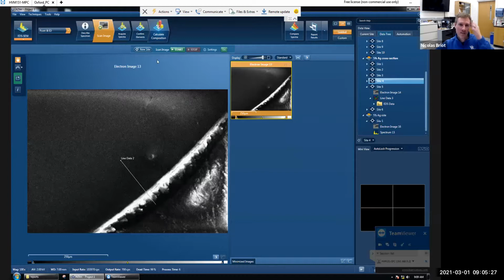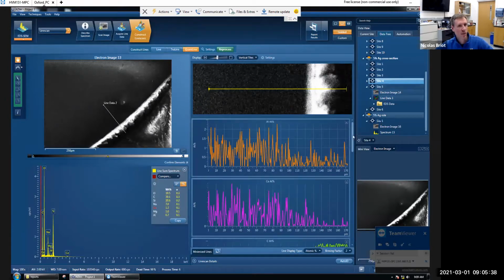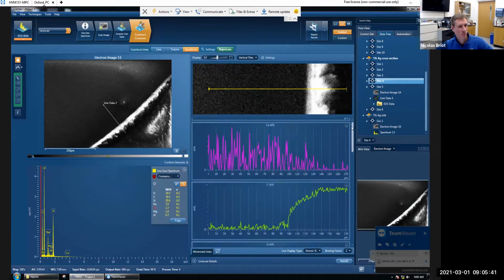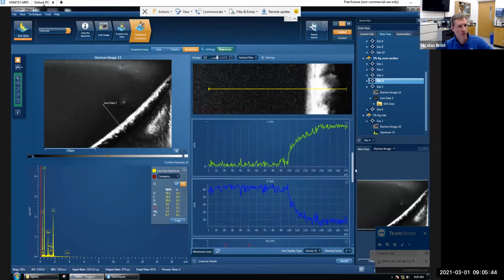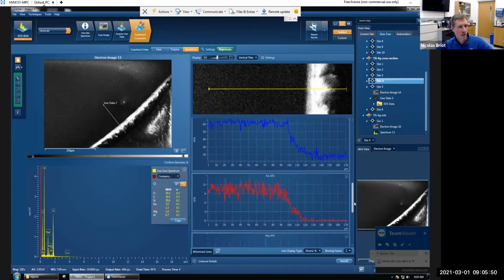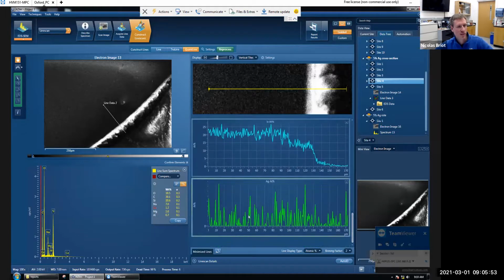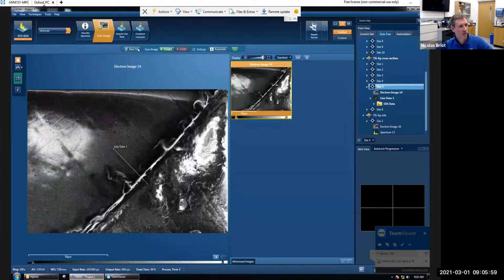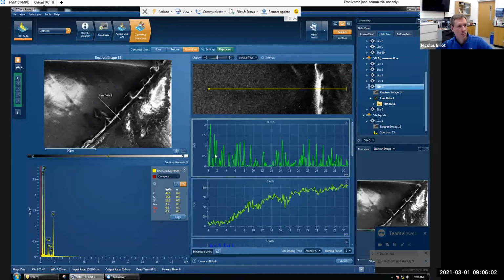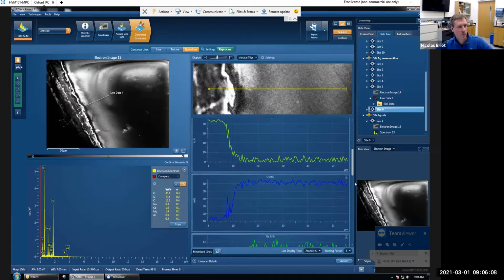And then we switched to doing line scan. So I zoomed in and really tried to capture the first 100, 150 microns within the sample. And we did a few of those. Where's the silver? So calcium, of course, at the transition, you start seeing a lot of carbon, a lot of oxygen inside. Oxygen, silicon, of course, it's glass, and sodium. But as far as the silver, it was pretty much just background noise. So we did a few line scans, again, at the surface. Couldn't really see silver close to the surface. Again, background noise. Where's the silver here?